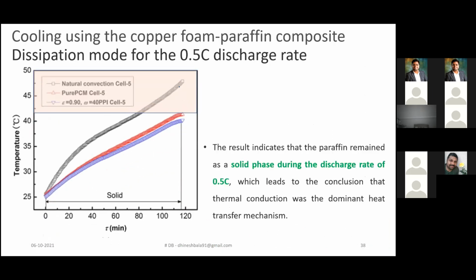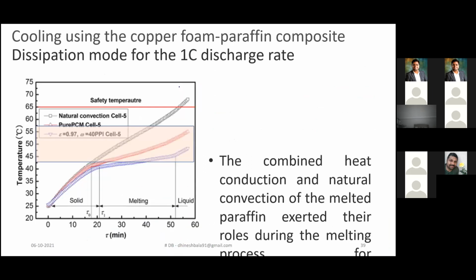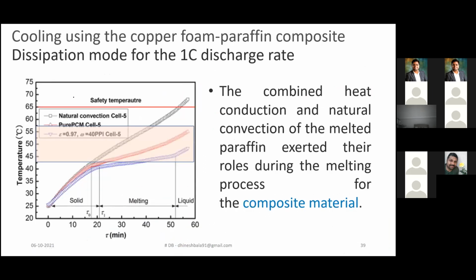And this is the pictorial representation for various discharge rates, and this will give you a much more interesting idea. The black color talks about air used as a cooling medium, the red color talks about the pure PCM, and the blue color talks about the PCM with the metallic foam. Up to 42 degrees Celsius, which is the melting point of your paraffin wax, all three look like a similar profile. In this zone, your PCM will be in solid form. After attaining 42 degrees Celsius, the zone of melting is initiated.